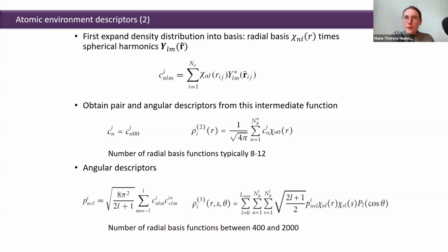Georg, and especially if you trained on a heating run, what does this mean for applying this force field at a constant temperature? Yeah, so if you have no phase transition in the heating, you should be careful. If you encounter some phase transition and don't want to learn that phase, you should not include it, because that gives a lot of additional information, which makes the force field too universal. That is not good, because with that you increase the variance of the force field and your errors get higher.